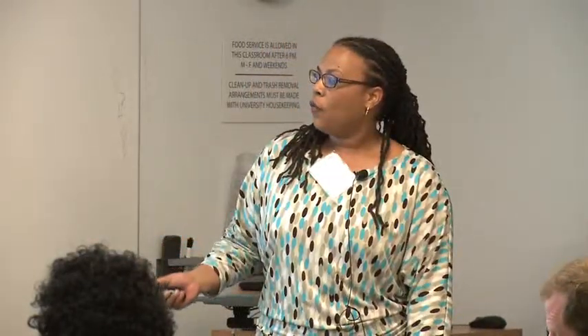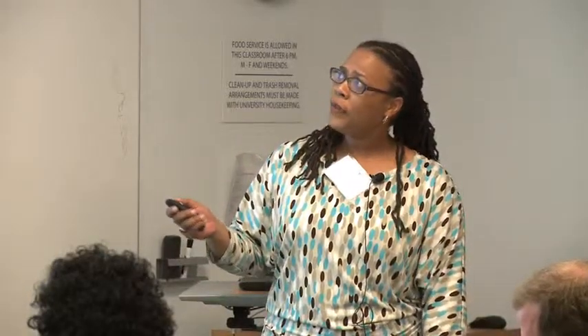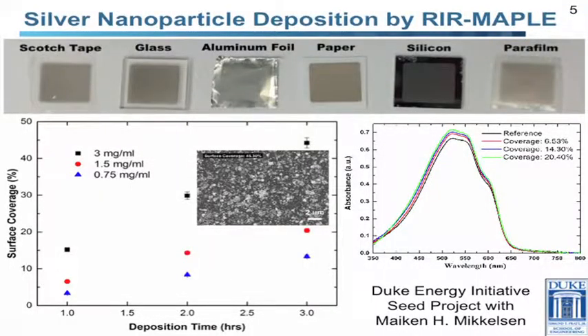So through a seed project that we received from the Energy Initiative and working with Maiken Mikkelsen in the physics and electrical engineering departments, we started looking at silver nanoparticles that were deposited by MAPLE. And so we actually demonstrated a lot of important capabilities with this project. One is that using the MAPLE process, we can deposit these films on just about anything. So scotch tape, glass, aluminum foil, paper, silicon, parafilm. So the process works the same way regardless of what your substrate is. And in a lot of chemistry applications, that's actually a very unique functionality.